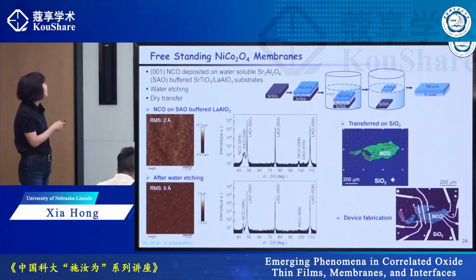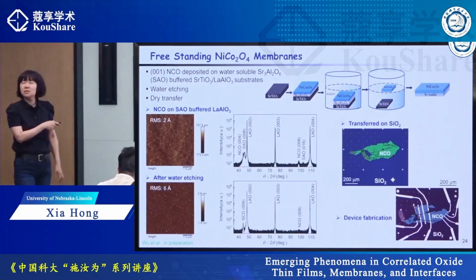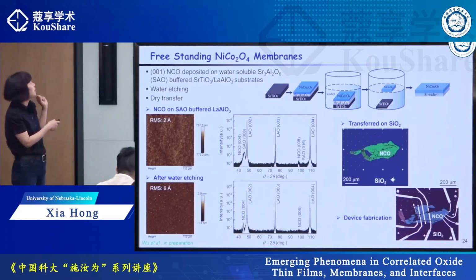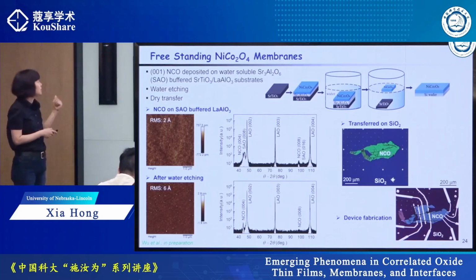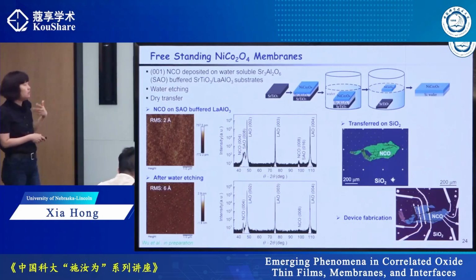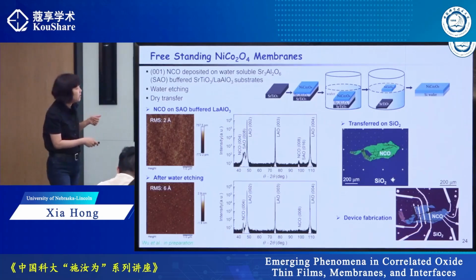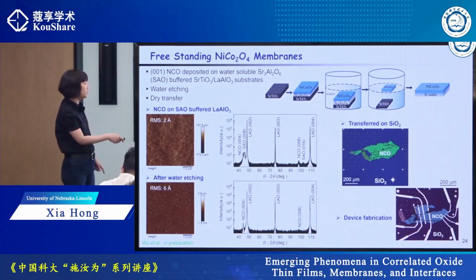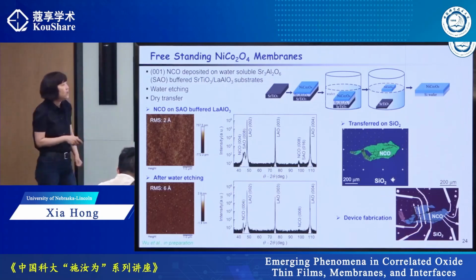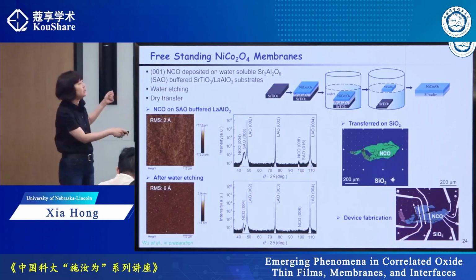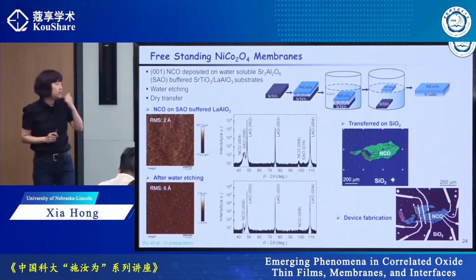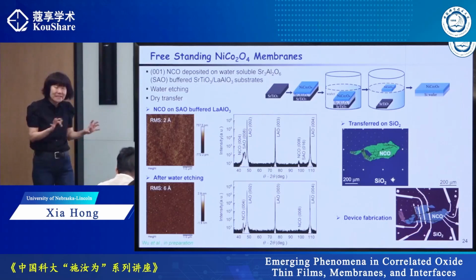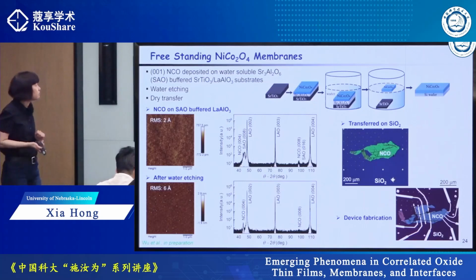You can see that this is nickel cobaltate epitaxially grown on a strontium aluminate buffered substrate. It's very smooth. After water etching, it becomes rougher, but it is still single crystalline. So this is the X-ray data. And in water, you can basically pick up this flake and do lithography, following exactly the procedure you would do with van der Waals material.